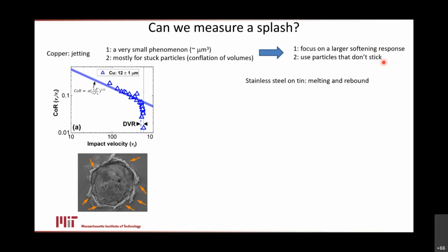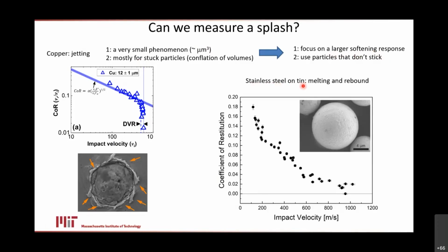So the experiments that I'm going to talk about today are ones where we've designed for this, and we're using a stainless steel striking pin for these experiments. A lot of this looks similar to what I've shown before. We buy very spherical atomized stainless steel powders. We shoot them at tin. We do this at many different velocities, and we've picked this system where there's really not a strong tendency for the particles to stick. Tin and stainless steel don't want to react with each other. They're not strong metallurgical reactants, so we mostly get bouncing.